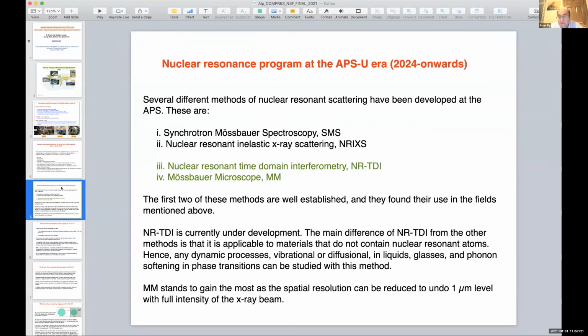The main difference of nuclear resonant TDI from the other methods is that it's applicable to materials that do not contain nuclear resonant atoms. So you are freed from the presence of iron or other resonant atoms, but also it frees up for liquids. So if you are interested in melts, if you are interested in glass transitions, if you are interested in diffusional liquids, we can provide you a new method that will give you relaxation times as a function of temperature and as a function of momentum transfer.